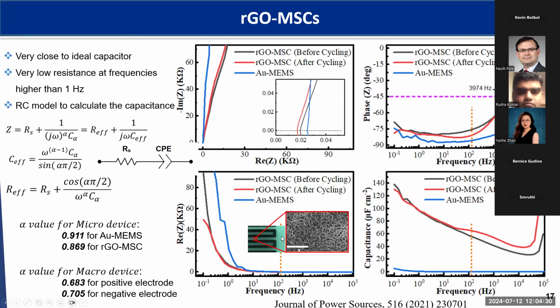We create the interdigital array. It's a two-dimensional system, but with very high surface areas. You can see from the capacitance, from the phase angle, from even the area capacitance, we see the dramatic increase of performance using our RGO-based microcapacitor.